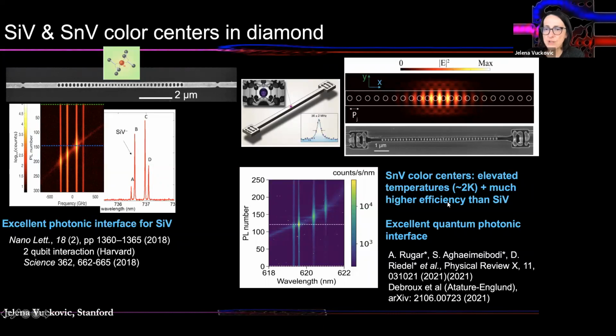But the reason why they're more interesting is because they can enable operation at somewhat elevated temperatures, because you have larger ground state splitting. So you are not really affected by phonons at temperatures of a few Kelvin. And they also have higher internal quantum efficiencies than silicon vacancies. So in principle, you should achieve all of the advantages of silicon vacancies, which have been somewhat the leading kind of qubits for implementation of quantum technologies in the color centers world for the past 10 years or so. You could implement all of those advantages using tin vacancies, plus operate at higher temperatures in closed cycle cryostats and have higher efficiencies, which is of course crucial for scaling.